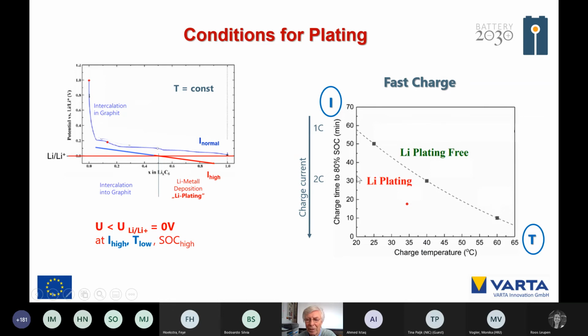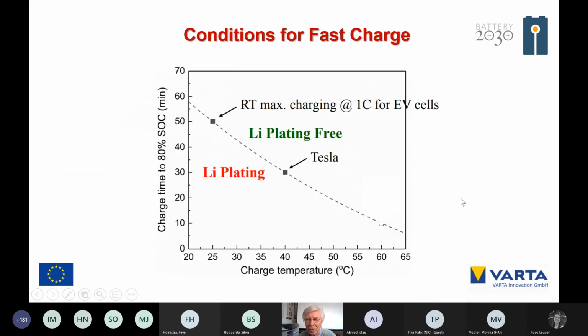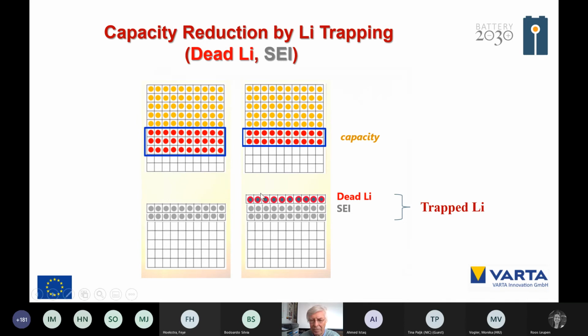So, for example, if you want to charge your battery in 30 minutes, about 2C, you need at least a charging temperature of 40 centigrade. If you want a 20-minute charge, your charging temperature should be 50 centigrade. And that is exactly what Tesla, for example, is doing to avoid lithium plating. Just before you fast charge the battery, the software heats up your battery to about 40 centigrade, and then you can charge with the high charging current. And the lithium we have seen is trapped lithium, and that reduces your capacity.